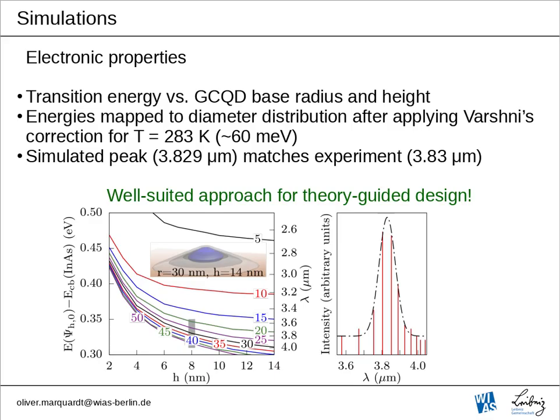Now for the electronic properties. The left side here shows you the transition energy of our systems for different graded composition quantum dot base radii and heights. So the radii are shown as numbers next to the respective lines, and the whole thing is plotted as a function of the height of the quantum dots. There's a typical quantum dot shown in the middle. The gray isosurfaces indicate the increasing antimonide content towards the tip of the graded composition quantum dots, and the blue area is the hole ground state in such a system.